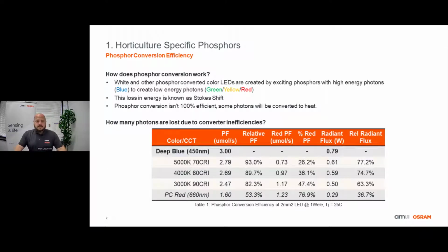So as I just mentioned, phosphor conversion works by absorbing some or all of those high energy blue photons and emitting low energy, longer wavelength photons. Now, this loss in energy is known as Stokes shift, and we'll get into the impact of that here shortly. But more importantly, the conversion is not 100% efficient, and this efficiency of a converter is going to depend on many variables, including the materials, the formulations, and of course the target spectral content.